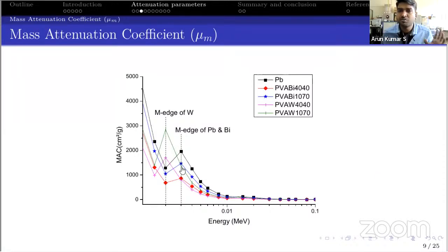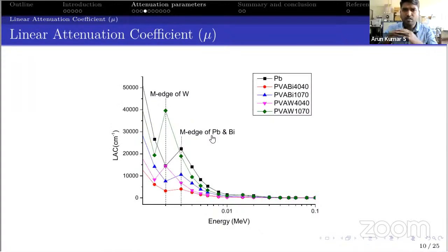I hope my cursor is visible to all. At the lowest energy range, we can observe the absorption edges of the tungsten PVA composite and the bismuth PVA composite. When compared to these peaks, the tungsten PVA composite peaks are much higher than the lead, the conventional material, which means it can give much more radiation opaqueness compared to lead. However, this is in the low energy range. Let's see further. Here I have taken the linear attenuation coefficient, which is similar to the mass attenuation coefficient.